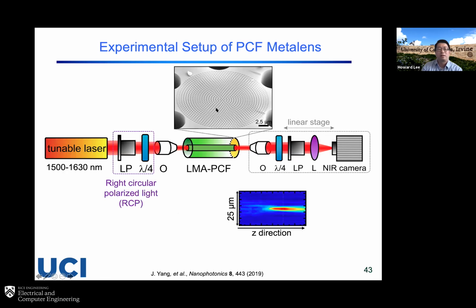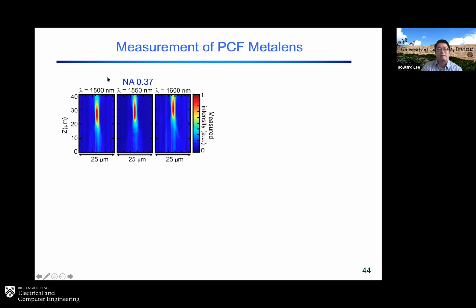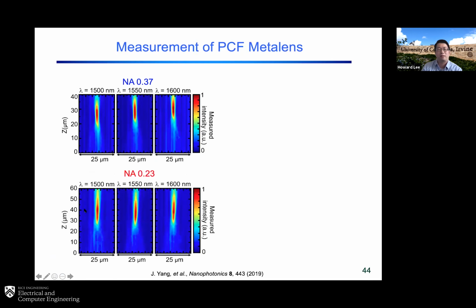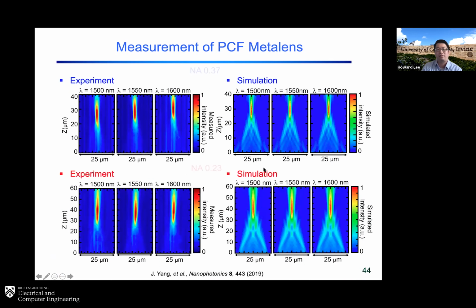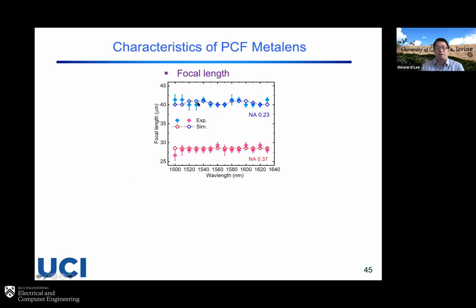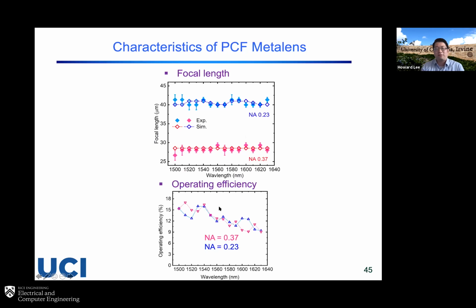So then we measure, for example, for different wavelengths, and we see for this lens, we have 30 micron focal length for different wavelengths, and for another lens, it's around 40 micron. They're quite consistent with different wavelengths. And compared with simulation, we have quite good agreement between simulation and experiment as well. So just to give you a little bit about the numbers, the focal lengths are quite constant in this telecommunication wavelength for two different lenses here. And the efficiency is also quite decent, around 15%.